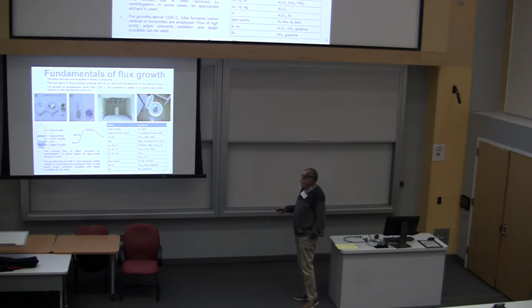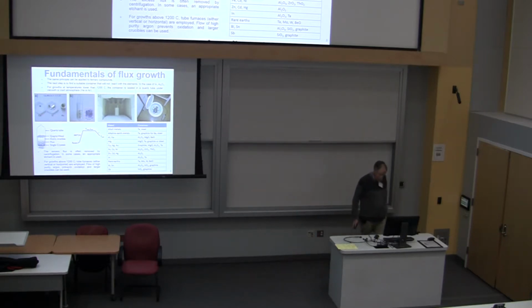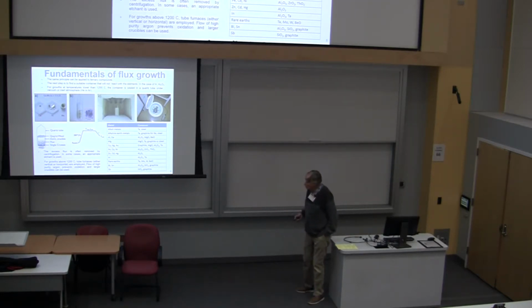Materials that people have studied at some length that you can grow from indium like that are ytterbium rhodium-2 silicon-2, which Steglich and company have done an enormous amount of work on, but also the crazy hidden order material, uranium ruthenium-2 silicon-2. But you have to go to quite high temperatures because these are very stable intermetallics, which don't have high solubility in the flux.